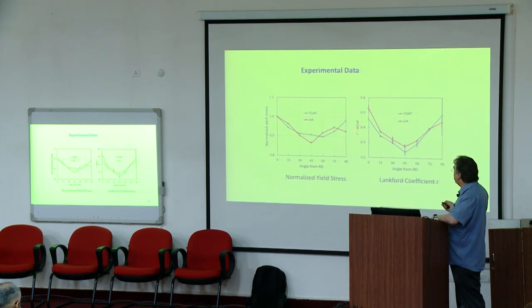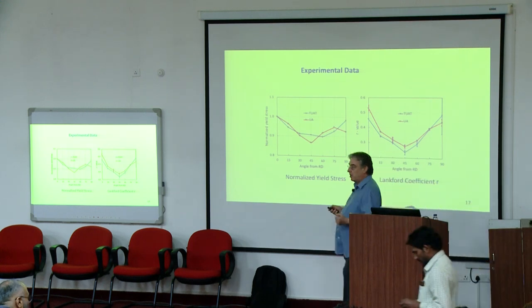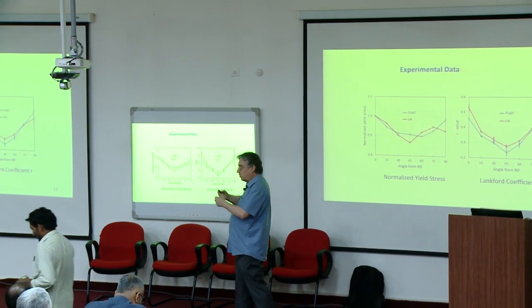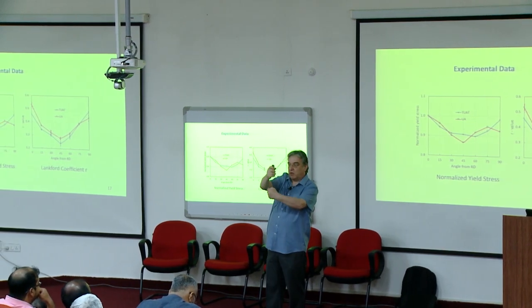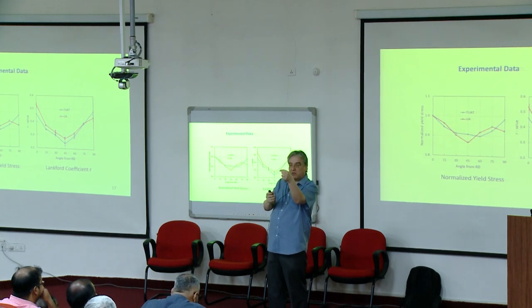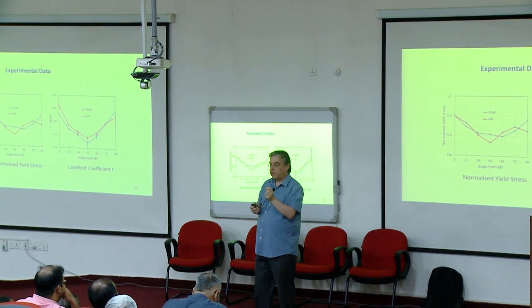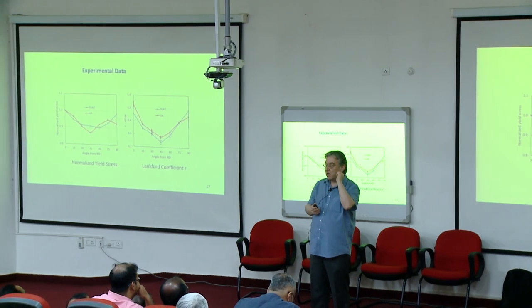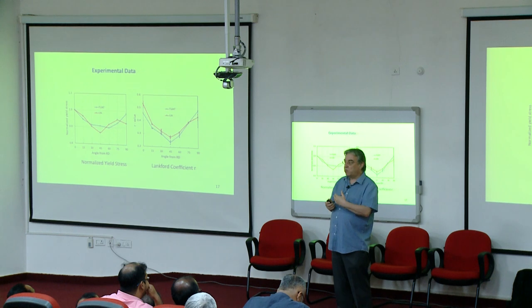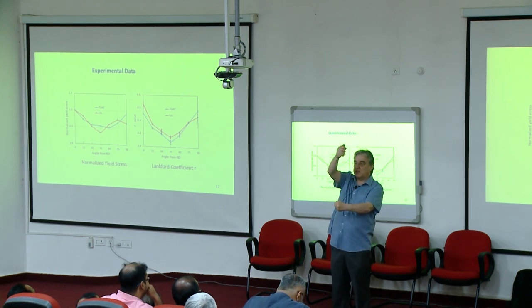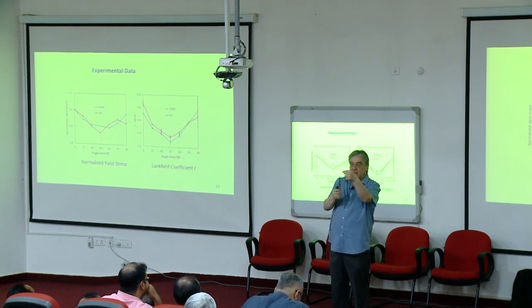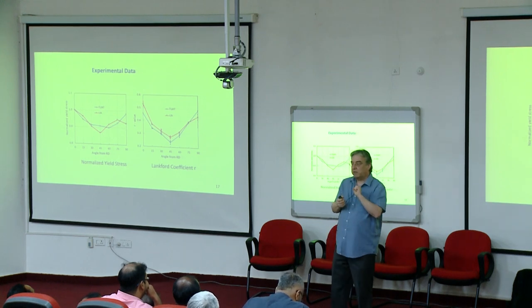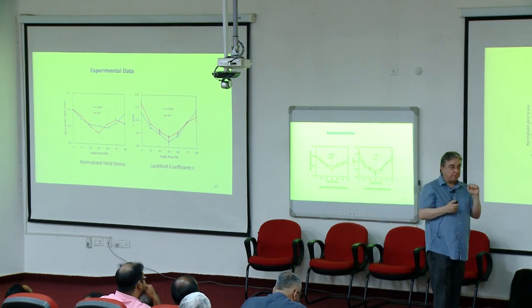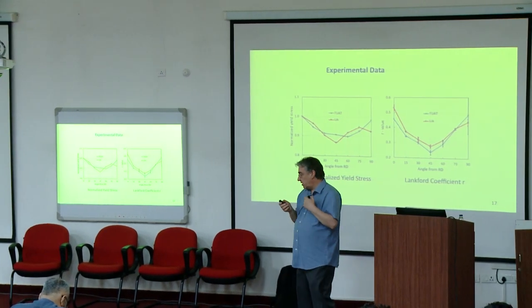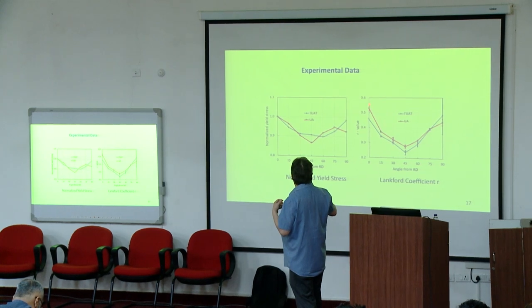This is another plot which is very important. On the vertical axis is the R value. This is a mechanical property which tells you the width to thickness reduction. If you do a tensile test on a sheet material, you are going to extend the length, and you are going to reduce the width and reduce the thickness. The R value is the ratio of the width reduction to the thickness reduction. So if you had a perfectly isotropic material, this R value would be equal to 1. That means that for a unit length extension, half of it is compensated by the thickness reduction, and half of it by the width reduction. Now, most materials, by the way you make them, are not isotropic. You can see that these R values for aluminium are not equal to 1. They are below 1.